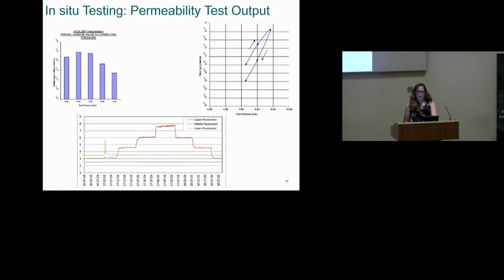This meant we could get images like the bottom graph. So the green and the blue lines, I'm not sure if you can see them, are holding steady pretty much, and that's above and below the test zone, which is what you want. You want the pressure to be constant there. In the middle of the test zone, for a packer test, you do 5 different pressures, and you can see there's quite clear steps on where we achieved the pressure, held it for the test, and increased the pressure.